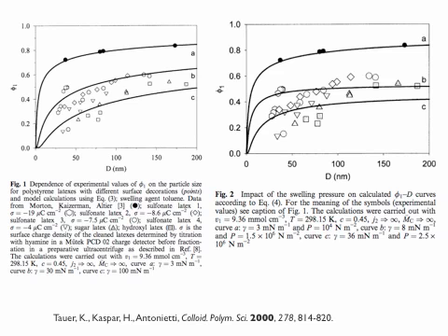So you could basically say, well, J2 goes towards infinity, and that's what they've assumed here. Crosslink density in this particular case is 0, so the MC goes to infinity. And then you have to have an estimate roughly what this interfacial tension is. So they plotted the data with different values of that, and then you get those lines. So it's a relatively okay fit.